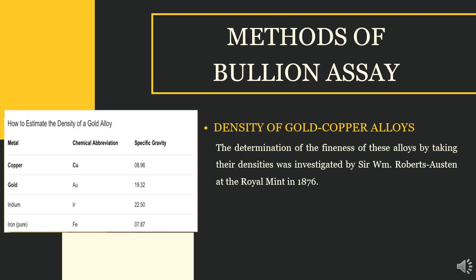The alloys examined ranged from 160 to 1000 fine and were made into discs which were all compressed to the same extent. The conclusion arrived at was that the fineness of large masses of gold can be deduced from their densities correct to 1 over 10,000 part. In the case of individual coins, the results are only approximate.